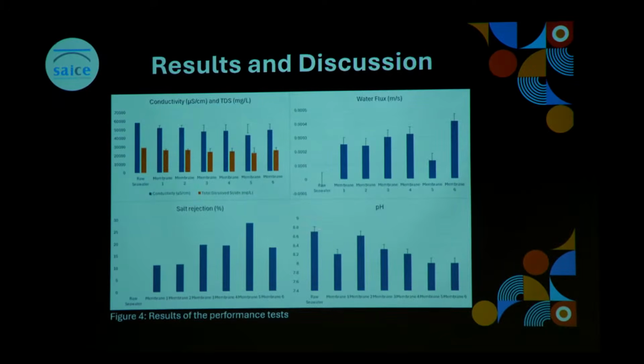Starting with raw seawater, we can see that it has a very high conductivity of nearly 60,000 microsiemens per centimeter, total dissolved solids concentration of nearly 30,000 milligrams per liter, and a pH of 8.7. All of these values are expected as seawater naturally has a higher amount of salts.